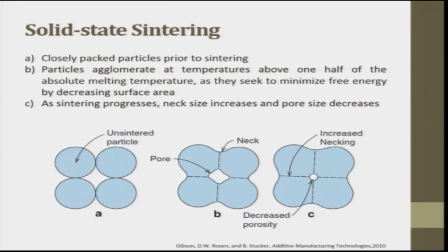So, when we look very close, A is closely packed particles prior to sintering, unsintered particles. Then particles agglomerate at temperatures above 1/2 of the absolute melting temperature as they seek to minimize free energy by decreasing surface area. In this, you can see there is a necking phenomenon happening on all four sides, and this leads to a pore in the center. And if you want to decrease the pore, then we take it to a much higher temperature. You see the pore size has reduced.